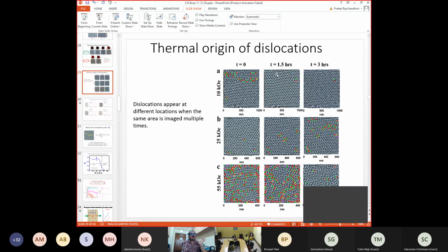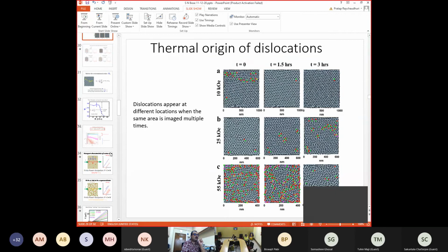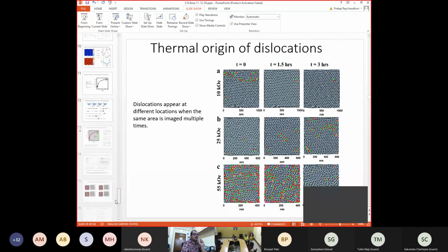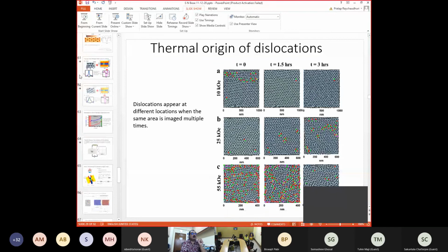Whenever we see motion, we see motion of all of them. We don't see some regions which remain static, and in between regions which have large motion. Having said that, we see those kinds of states in one situation, at very low fields. At very low fields, we see polycrystalline domains. At higher fields, we don't see that anymore. In those polycrystalline domains, we sometimes see motion in the domain boundary.